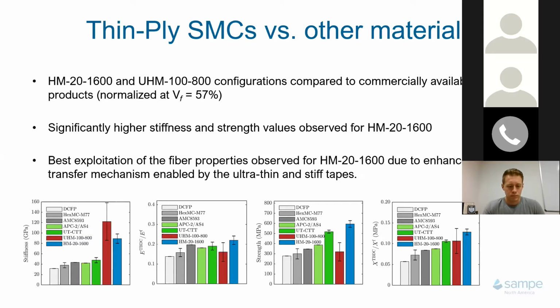But the interesting part is also to compare the second graph, where we compare the stiffness of the SMC divided by the stiffness of the fiber itself. Here we see that for this configuration, which was also made with thick tape, this ratio is lower than, for example, the blue specimen, which was made with very thin tapes of 20 microns. This means that with the thin tapes, we are able to achieve a better exploitation of the fiber properties than with thick tapes. And that's what is interesting here.